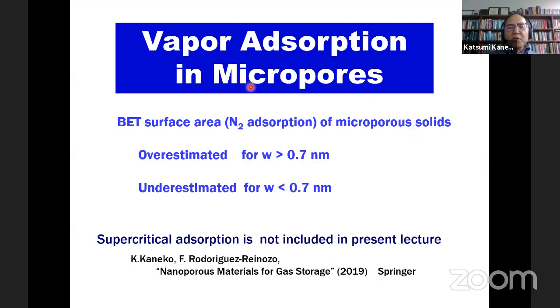So vapor adsorption in micropores is very important, and the BET surface areas are also very important. But for micropore systems, if the pore width is larger than 0.7 nanometers, the BET surface area is overestimated. In some cases 40% overestimated. Huge overestimation occurs. And less than 0.7 nanometers, underestimated.